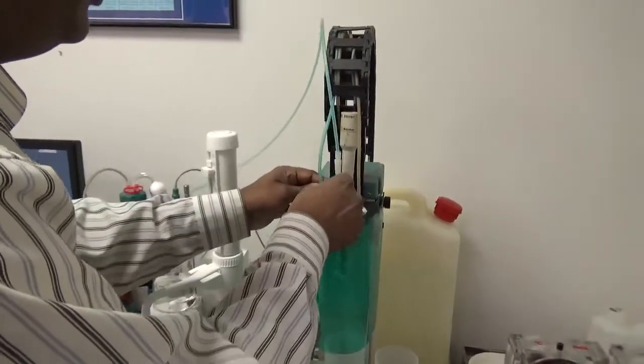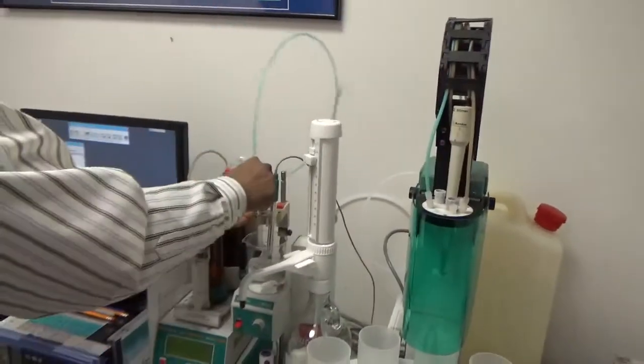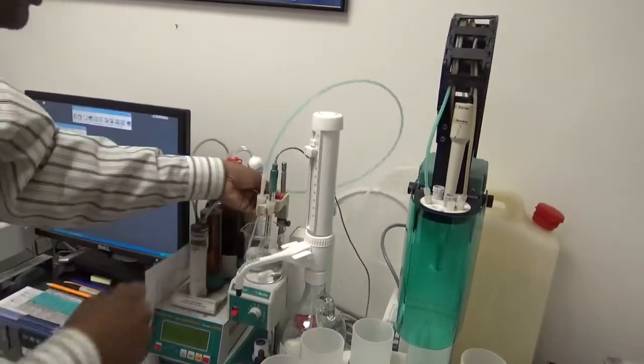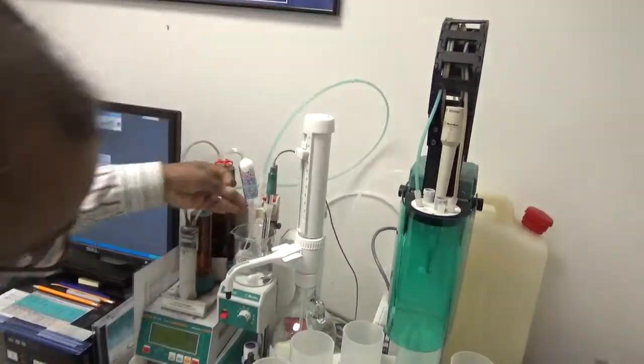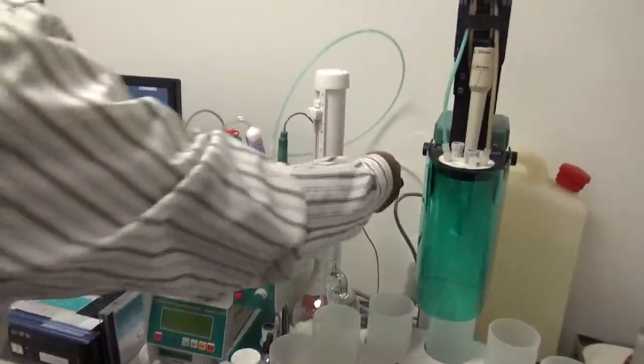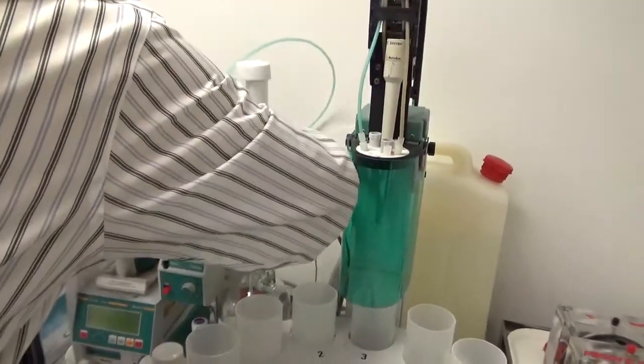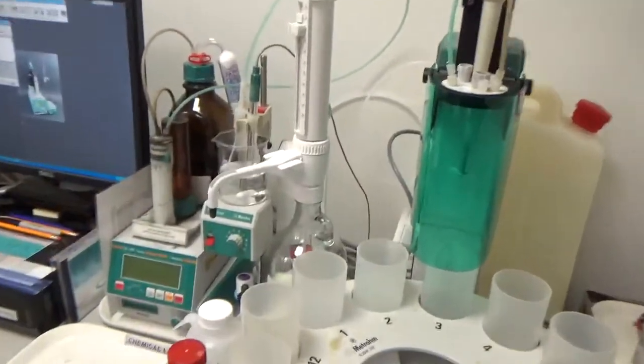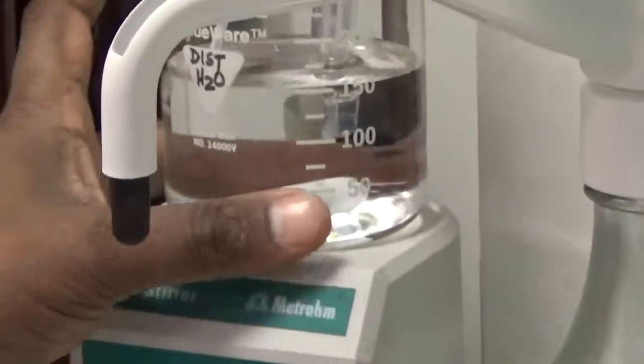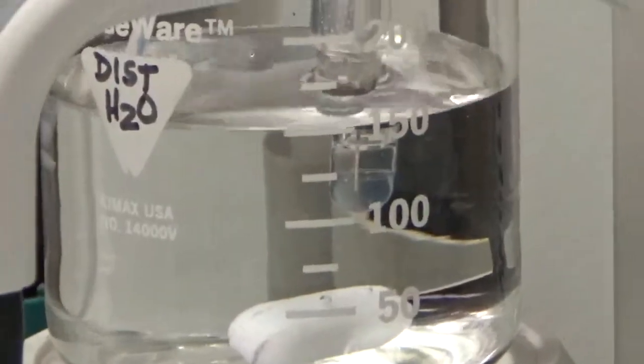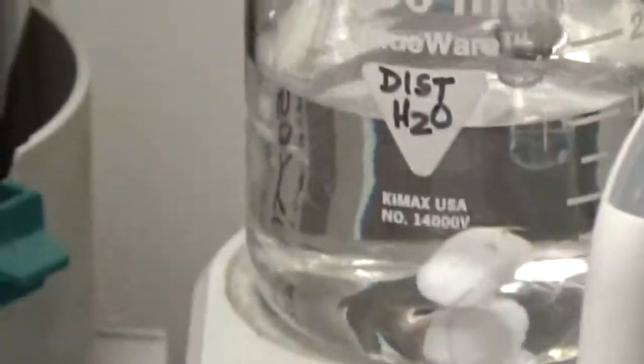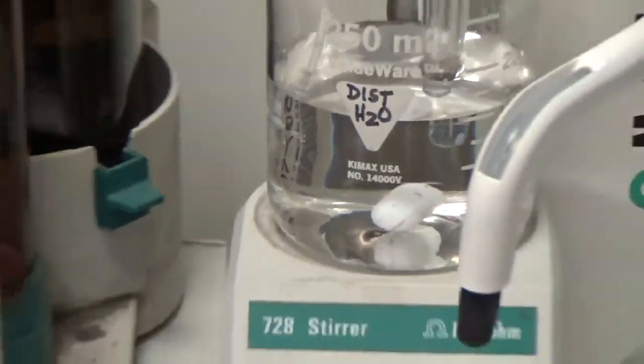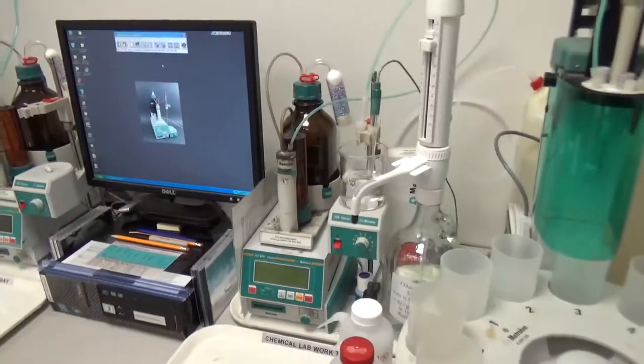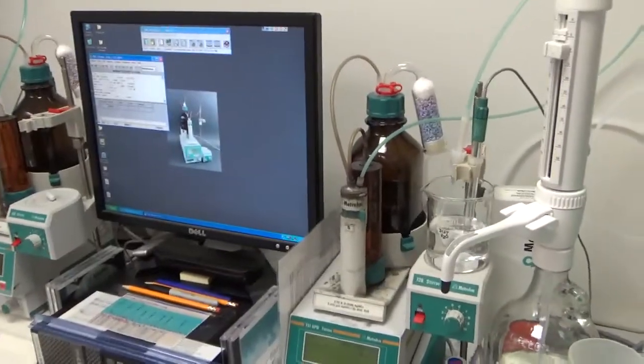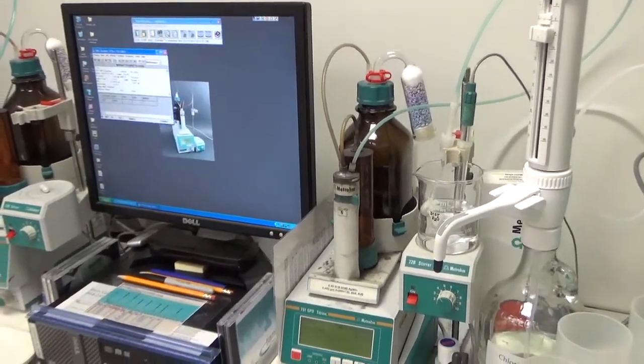We take the burette out of there, add the burette there, and we go down. Make sure the entire tip of the electrode and the burette are under the solution. They both are under solution, but they're not touching the stirrer bar. So once that's ready, we don't have to run a macro at this time because we don't have multiple samples. We have just one sample. So we just go to 751 and we say start the titration.